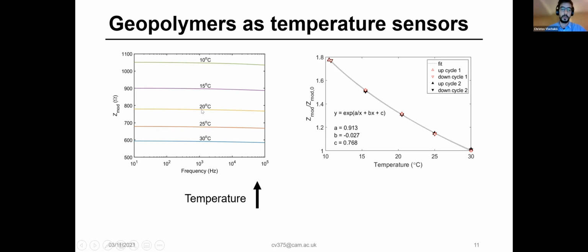Something you probably already noticed is that once the temperature starts increasing, so we go from 10 to 15 to 20, 25, and 30, the resistance of the material actually decreases. And the reason for that is increased ion mobility. So basically what this means is, as the temperature increases, the ions move faster, and the faster they move, the lower the resistance. And likewise, the opposite occurs. The lower the temperature, the slower the ions move, and therefore the higher the resistance will be.